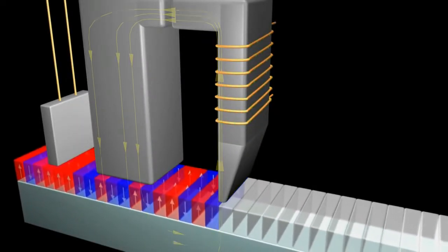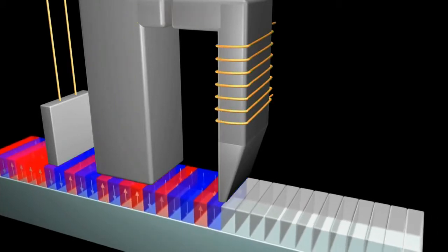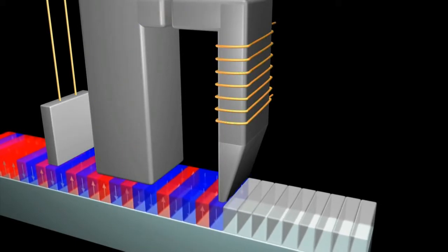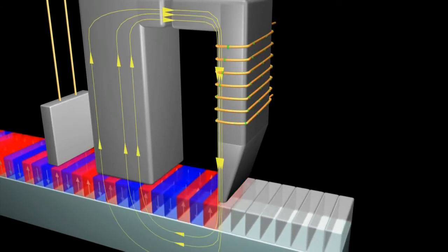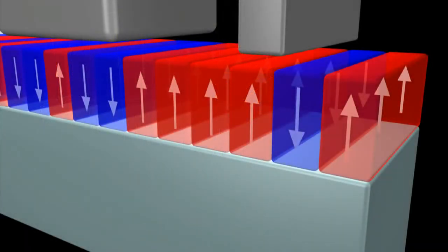Hard drives now use perpendicular magnetic recording, where the magnetic field either points into or out of the disk, rather than along the disk. This allows for sectors to be closer together on the track, resulting in a higher data density. This advanced data storage method is made possible by the unique structure of cobalt, the metal used in the magnetic layer.